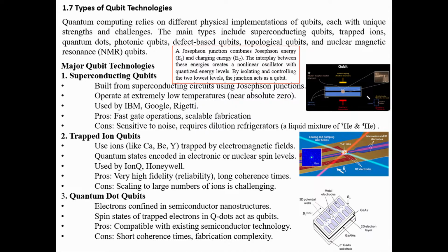Because of that there will be a strain, and while releasing that strain, your quantum dots, nano dots, zero dimensional dots, will form by the process of self assembly.